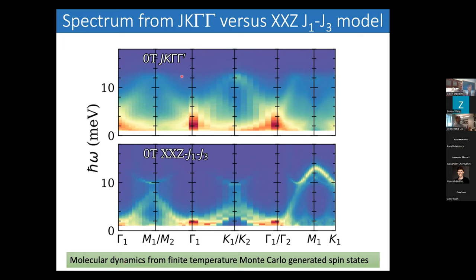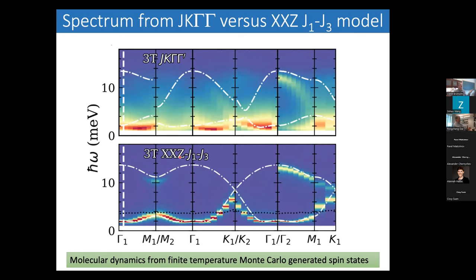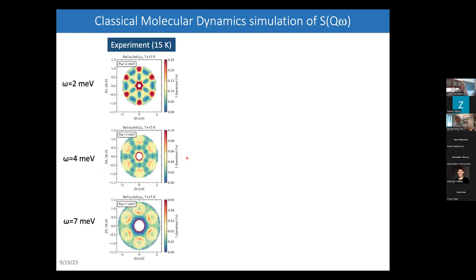And so he's taken the models that are closest to accounting for the data, though we know this model doesn't actually account, for example, for the ordered state. And then he does this molecular dynamics to get the corresponding excitation spectrum at 0 tesla. And then when applying a field of 3 tesla, what is found is an excitation spectrum which is quite consistent with what is seen experimentally, fairly sharp modes of excitation. Whereas the J, K, gamma, gamma prime model in molecular dynamics would have very strong continuum scattering. So a classical effect, but also something which is not seen experimentally at 3 tesla. So it's another indicator that we really are talking about a J1, J3 model.